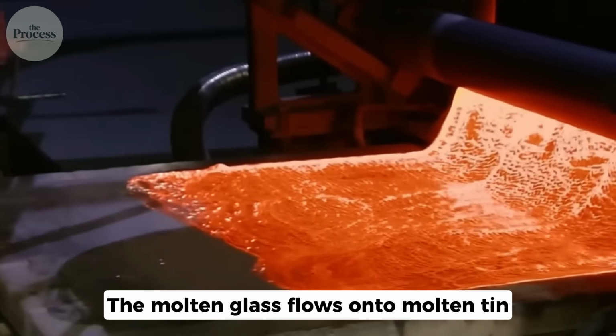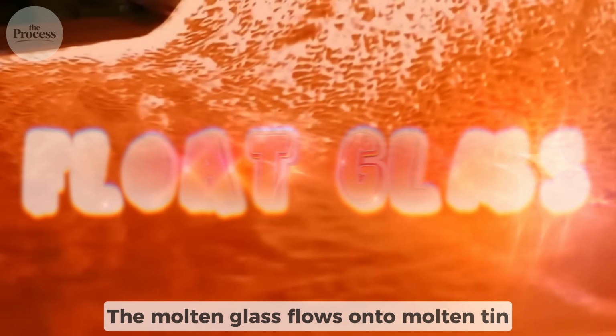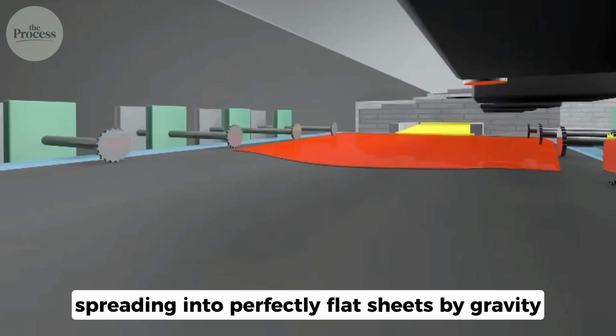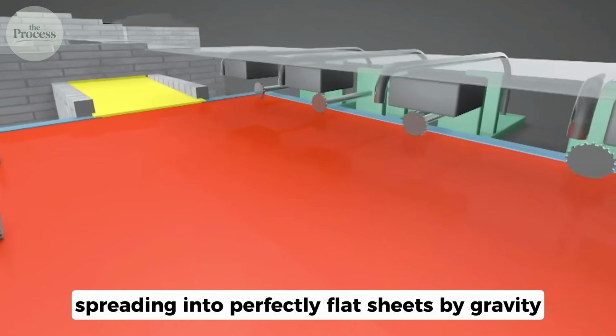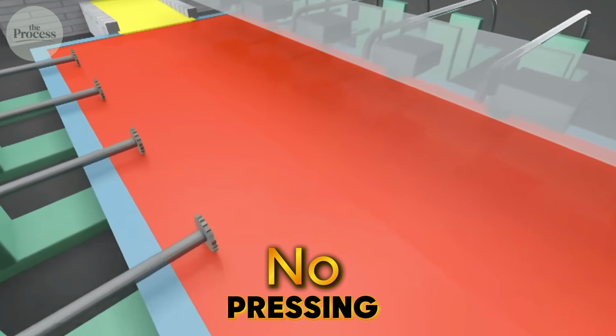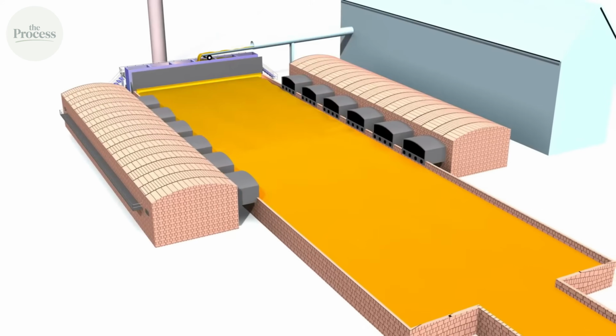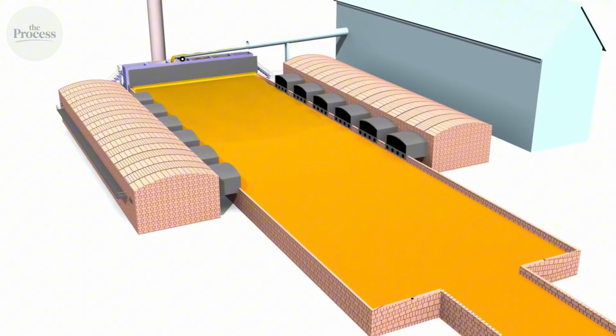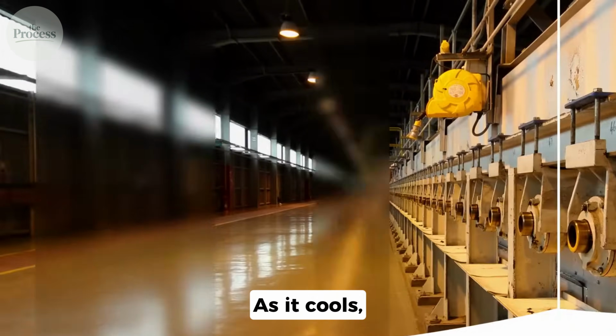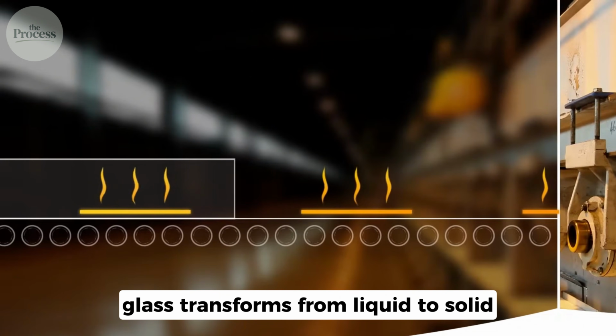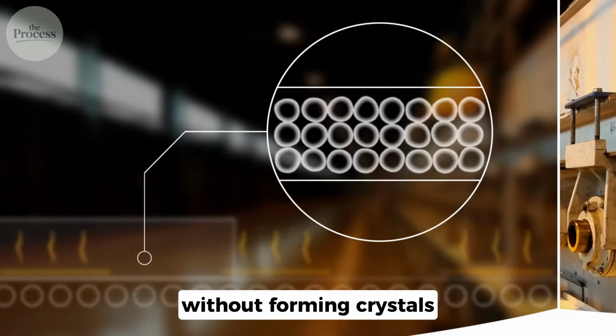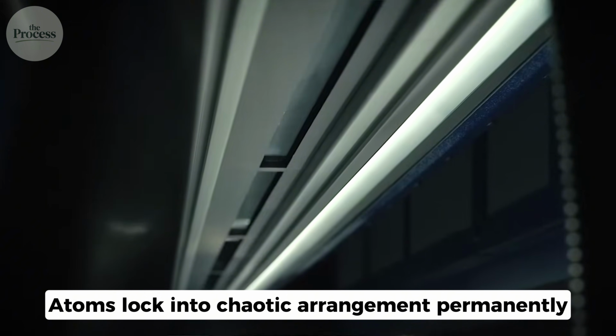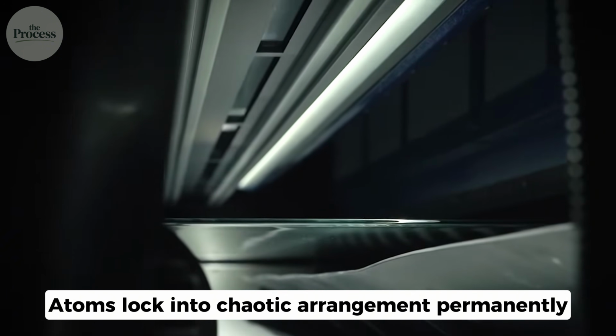The molten glass flows onto molten tin. Float glass. Tin is denser than glass, but liquid at processing temperature. Glass floats on top, spreading into perfectly flat sheets by gravity. No pressing, no polishing. Physics creating flawless surfaces. As it cools, glass transforms from liquid to solid without forming crystals. Atoms lock into chaotic arrangement permanently.